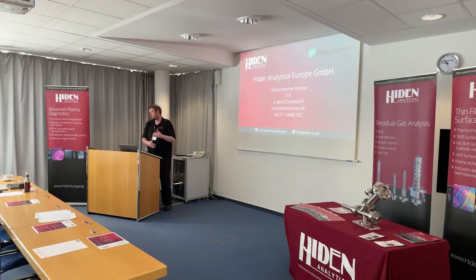So we have a standard test routine. We try and position the EQP when we're testing it to send out to a customer in the same position, so that we can use various measurements that we take as benchmarks to make sure it's performing properly. That's the main function of that chamber. But if we had a special request to do that as part of the testing process, then yeah, we could fit a Z translator to it and position it differently.